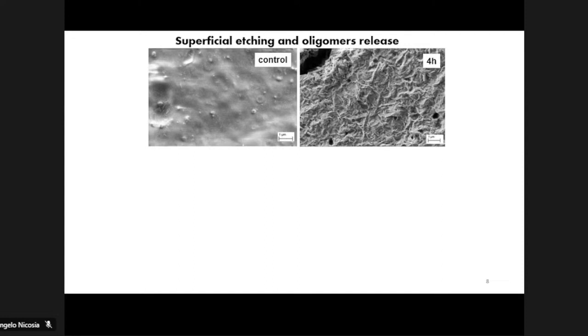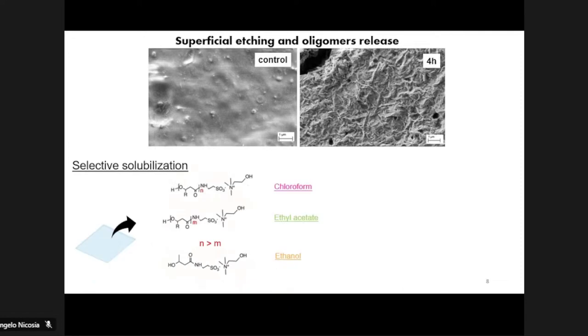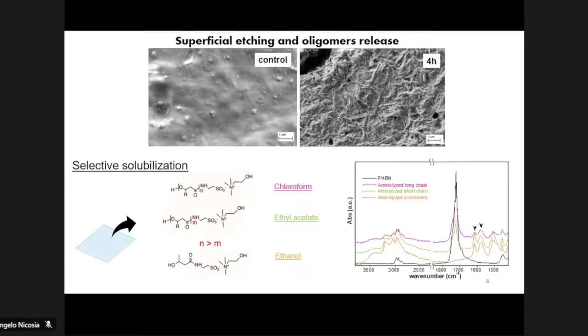And the hypothesis is that by pushing the reaction to higher times, the degradative nature of aminolysis prevails, with a consequent surface etching and the release of oligomers in the reaction medium. To verify this hypothesis, the reaction medium has been fractionated through selective solubilization, and 3 different fractions were collected. The first fraction was collected in chloroform and is composed of aminolyzed long chains, while the second fraction was collected in ethyl acetate and is composed of aminolyzed short chains.